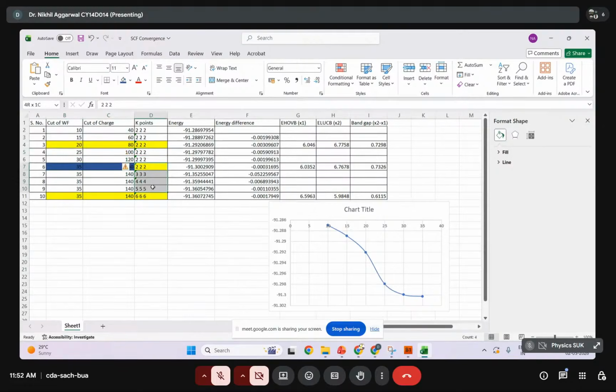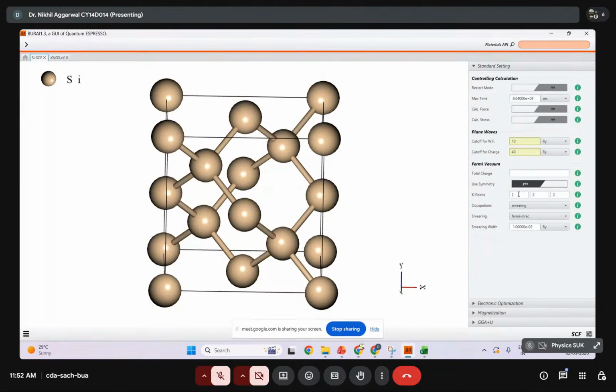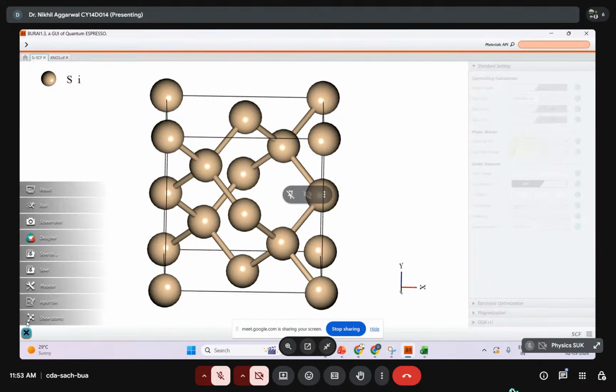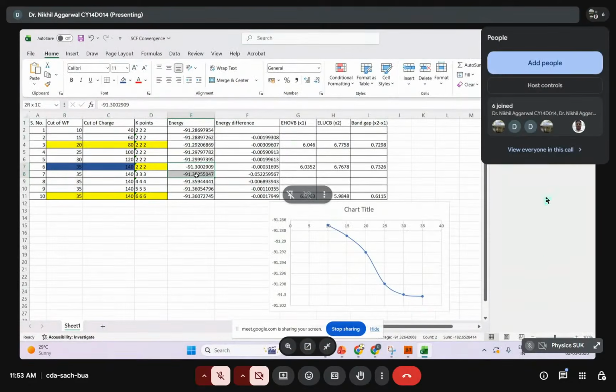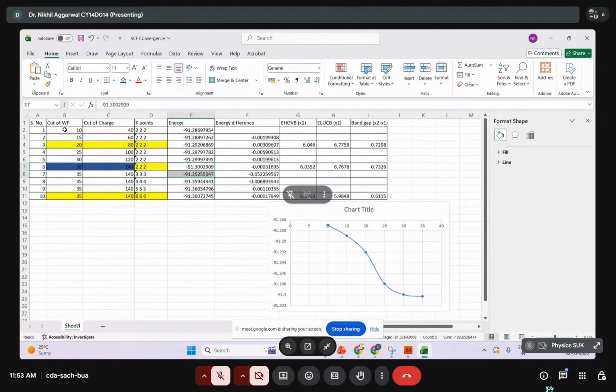How? Progressively increase the values like this. I'll show you. We had done the first calculation using a combination of K as 2 2 2. Next, I'll take a combination of 3 3 3, which means we are allowing more K points in a given Brillouin zone. Run. Taking more K points in a given Brillouin zone further decreases the energy of the system. So in summary, for the SCF convergence calculation, you need to find out the cutoff values of kinetic energy, wave function, charge density, and the K point. And accordingly, you will get the value of the energy.